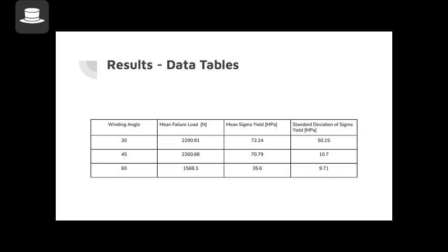to this data set. Our winding angle of 60 degrees, as we suspected in our hypothesis, was the lowest failure load at 1568 newtons with a sigma yield of 35.6 and our standard deviation of 9.71, which is very close to the 10 we got with the 45, indicating that this is a fairly reliable data set.